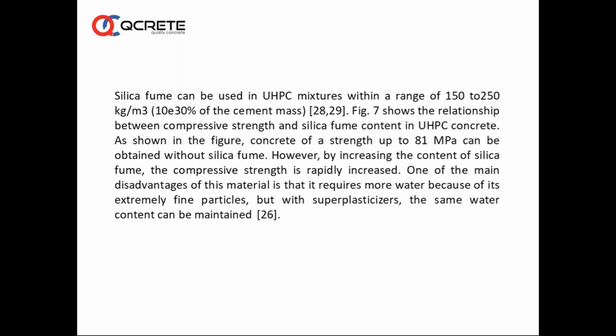But the advantages are plenty. Even though you can make concrete without microsilica and get some high strength, many times in our experience, we can say microsilica is like an insurance. Whatever happens, if some mistakes happen during production or during transportation, microsilica will take care of that and give additional strength, as a strength boosting material as the age goes on, and 28 days and beyond also it will improve the strength, and it is a material accepted worldwide for use in high strength concrete and also ultra high performance concrete. So even though it requires more water or more admixture, it is a product which is used worldwide wherever high strength, high chemical resistance, low RCPT values are required.